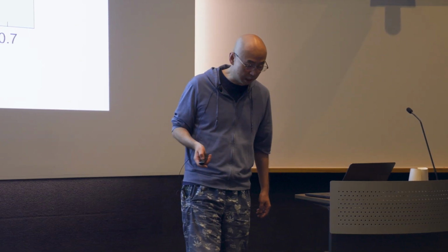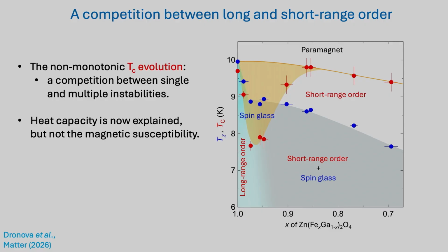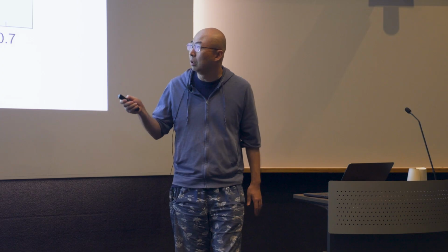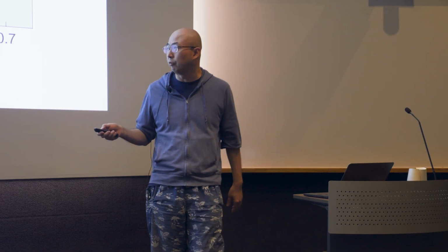So now we can start to understand the phase diagram of this system. What we have in the heat capacity evolution is that very close to the x equals 1 position, we have long range order. When you have more disorder, the long-range order becomes much more fragile. It takes lower temperature to stabilize. So the ordering temperature becomes lower and lower because the disorder makes the growth of long-range order more difficult. However, it still dominates over your short-range order. Only when you have more disorder does short-range order win over.